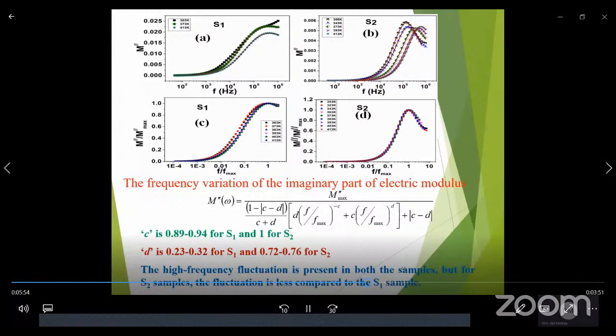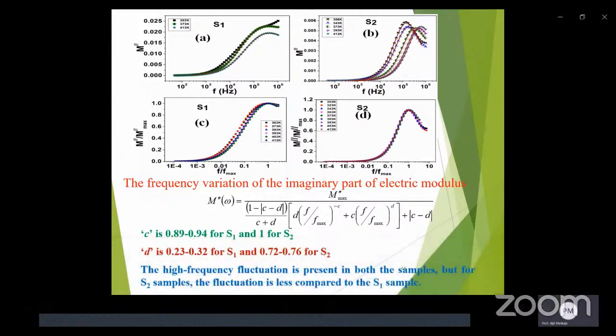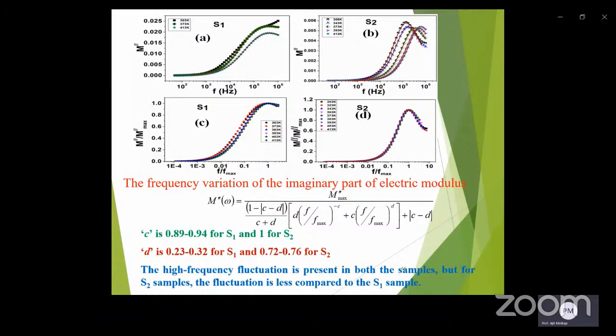The value of parameters C and D in the equation indicate the deviation from Debye model at low and high frequency region. The analysis of the data suggests that the deviation from the Debye model is less for S2 sample compared to the S1 sample.